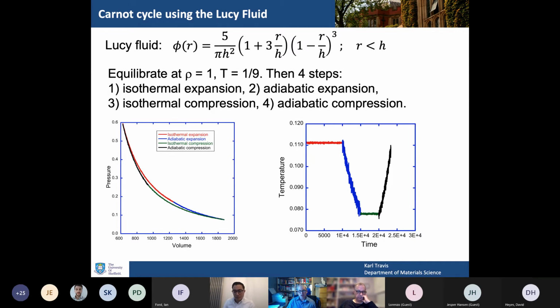I've developed this as a teaching tool, actually. This is hot off the press. You can start at a particular equilibrated system. I then underwent isothermal expansion, that's the red curve here, then adiabatic expansion, then isothermal compression, and then finally the black curve, taking it right back to the start, is adiabatic compression. The point is that you can control the expansion rate perfectly. So if you do it sufficiently slowly, each leg of the run is essentially reversible.